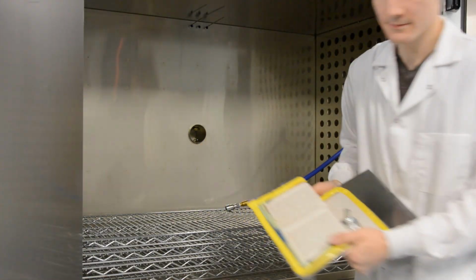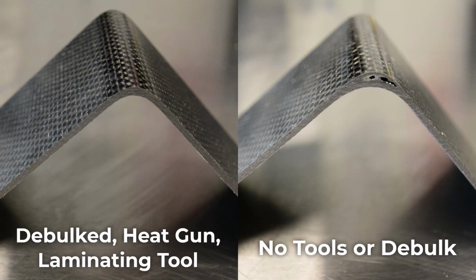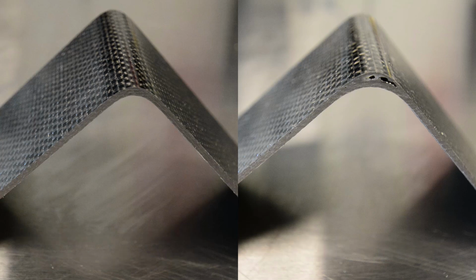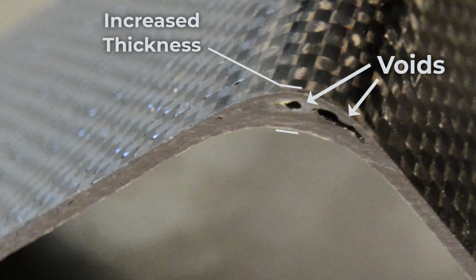After curing the two parts, we can see that the plies of the debulked part are well positioned and closely follow the curvature of the tool. The plies of the second part are not well positioned and are bridged over the corner, creating voids. The bridging of the outer plies prevents the corner area from being exposed to full consolidation pressure, resulting in reduced properties and the pooling of excess resin.